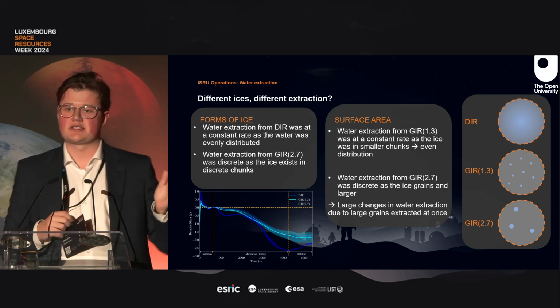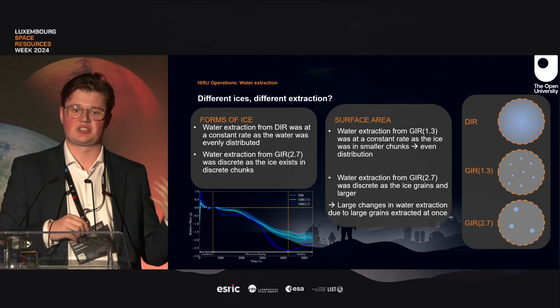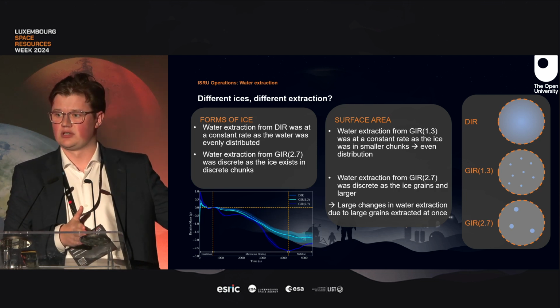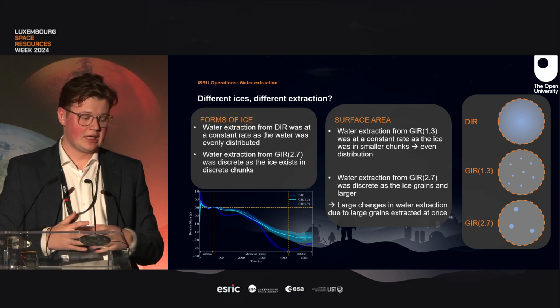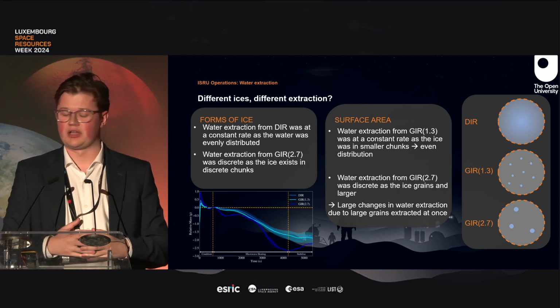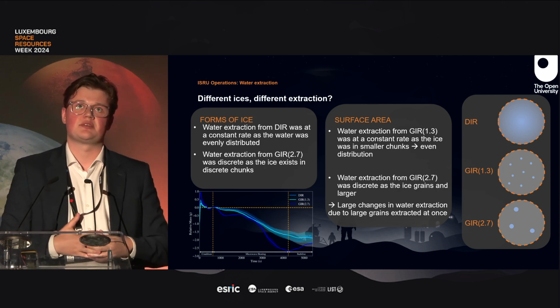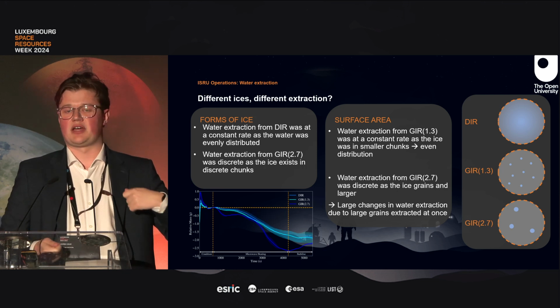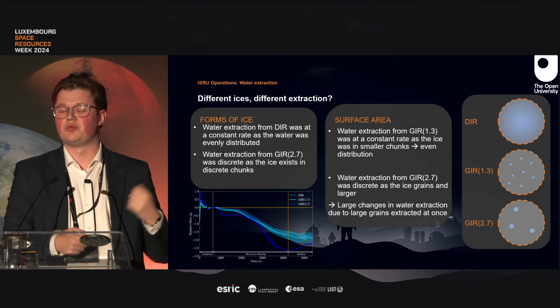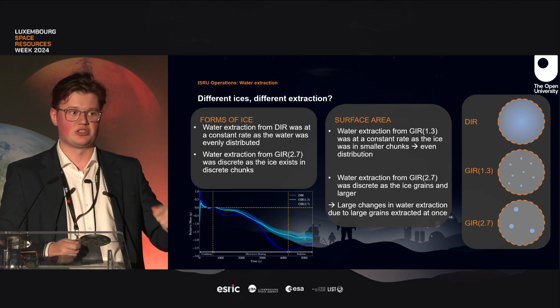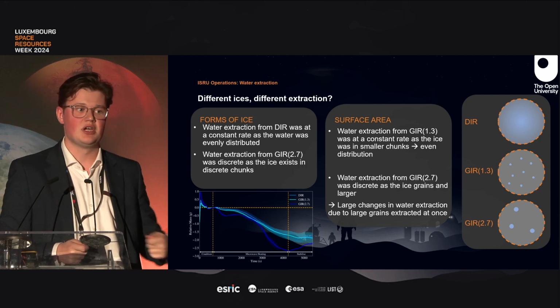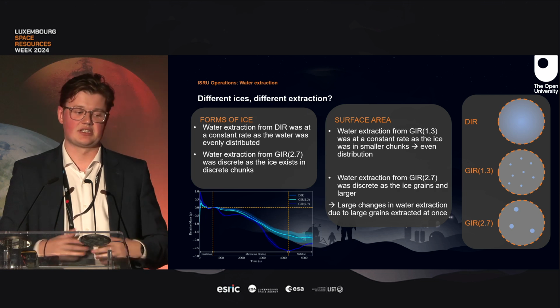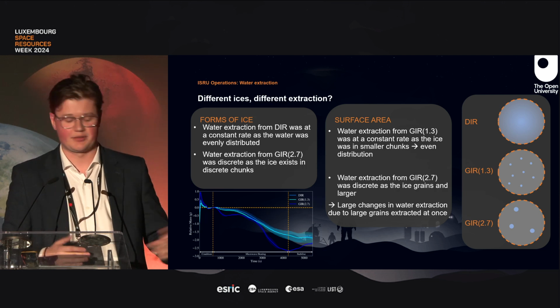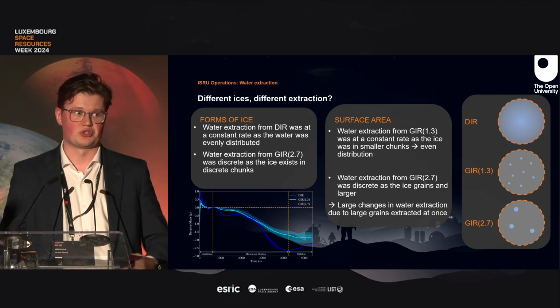I think, firstly, this highlights the power of the dynamic mass instrument, and before this, we weren't able to see what was occurring within the microwave heating time allotment, and now we can see what's going on. So that was nice to see that it was a worthwhile endeavor. And I think it also shows that there's something to be said for extraction experiments also sort of as a cycle can almost act as a prospecting technique, where the mass loss can tell you what sample type you may have. With enough lab time and with enough variations in your sample type, you may be able to send something like this to the lunar surface and tell you, whether it be through mass loss or pressure increases, what you're actually extracting at the same time as extracting it. So you can aid yourself in both space resources, but also the lunar science that's going on at the same time.